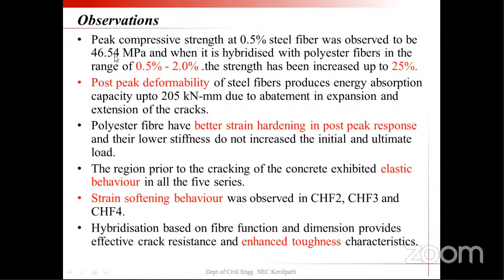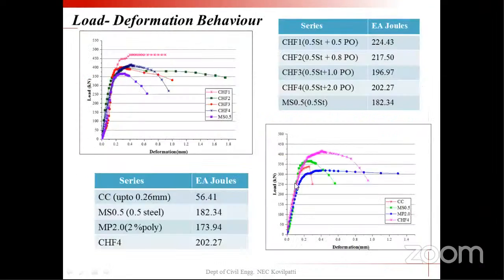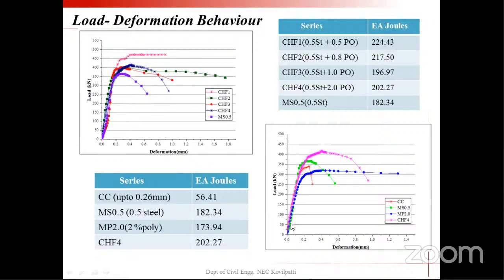So these are some salient points we observed from the diagram, the load versus deformation curve. The peak compressive stress was observed up to 46, and the post-peak deformability is a very specific character of single FRC or hybrid FRC. You can see in the CC control concrete, there is no post-peak, it just reaches the peak and sudden failure happens. And MS 0.5 is a steel fiber, and you can see very good softening characteristics. And MP polyester 2 has also shown strain softening behavior. Also in this CHF4 series, you can see strain softening as well as strain hardening.